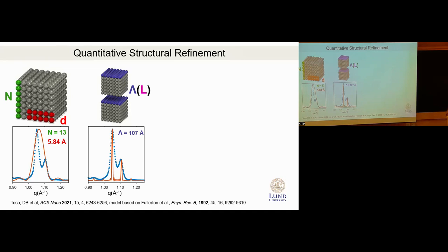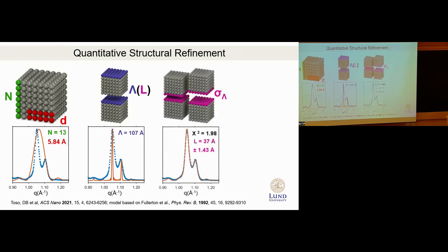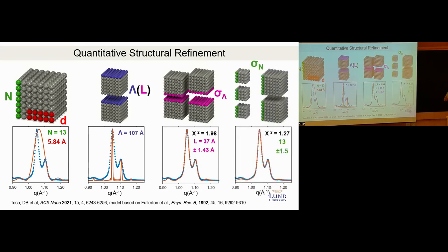But that's not what we see. We see them much broader, and this is where the disorder starts playing a role. On top of this, we introduce a normal distribution of disorder in nanocrystal positions, basically a very small variation in phase shifts, which broadens the calculated signal, but lets us numerically fit the value of interparticle distance and, more importantly, its fluctuation. And lastly, because there is a size distribution of nanocrystals, we can represent our sample as consisting of multiple-size pure superlattices, just to simplify the model and the calculation, and then add this effect on top, and also determine the average number of planes in a nanocrystal and its standard deviation.